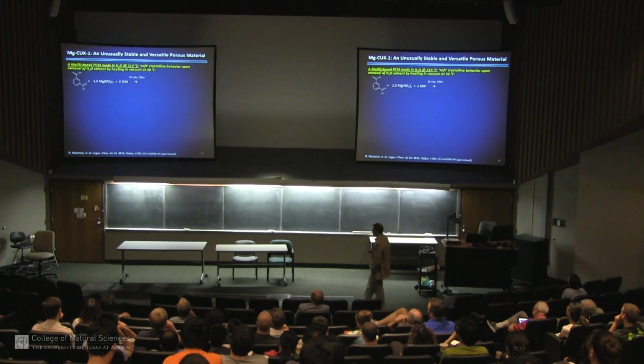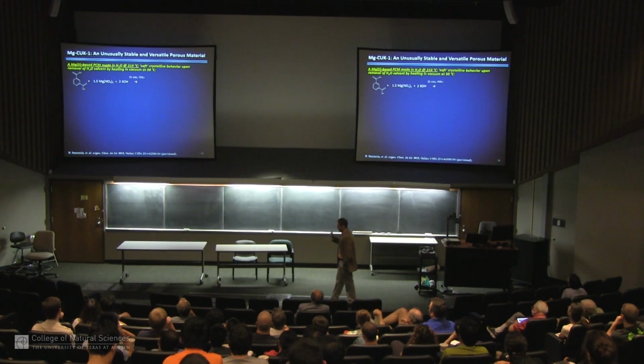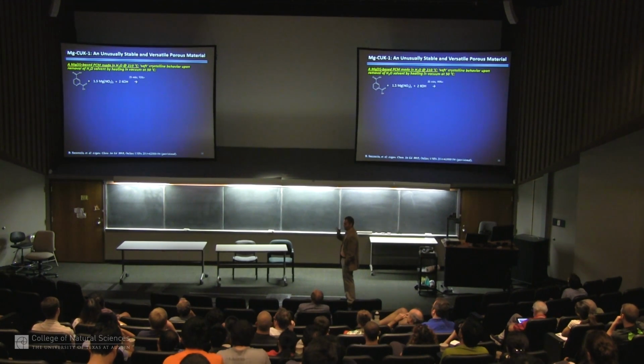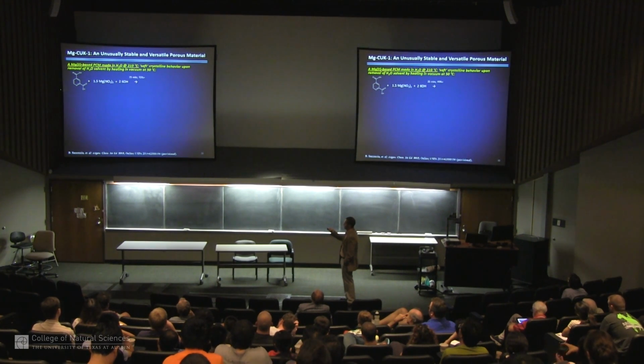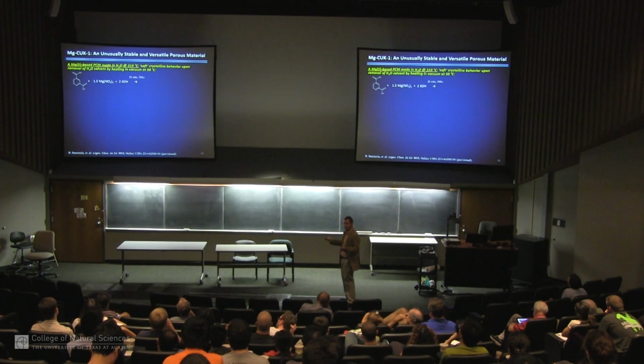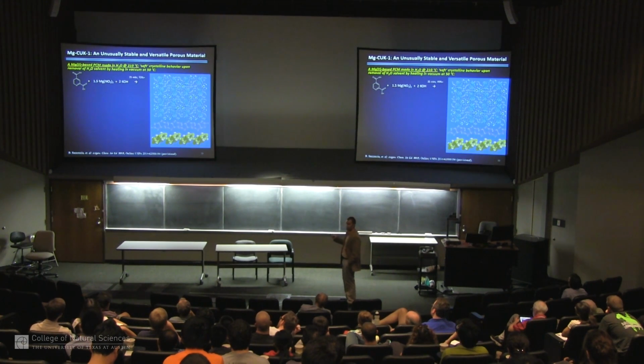carbonyl type species. The last couple slides on this area are a little bit separate, but just to give you a flavor for what we're trying to do in making water stable and very cheap and upscalable materials. This is amazing that this reaction works so well. A ligand that's a little bit cheaper and easier to make, magnesium nitrate, one of the cheapest metal precursors you could come across, potassium hydroxide, pure water as the solvent, nothing else, stuck in the microwave for 35 minutes, and out comes this amazing porous material, highly crystalline material.